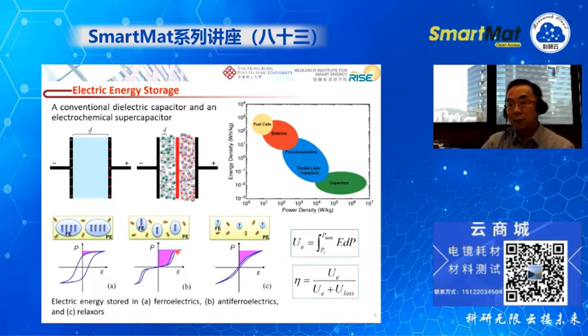And another thing is, if you look at the hysteresis loop, you see for a capacitor, you need to charge the capacitor before use. So when you do the charging, the energy required should be integrated along this charging curve. When it is removed, it will be discharged from the above curve. So there is a difference between charging and discharging. The difference in energy corresponds to this white area, and this corresponds to the energy loss during the charge and discharge. And for practical application, we wish this type of loss to be as small as possible. So ideally, we need to have a very slim hysteresis loop. And this slim hysteresis loop can be achieved in a relaxor type of the ferroelectric or anti-ferroelectric material.